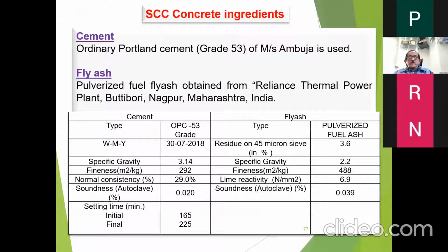Ordinary cement was used. The fly ash used was from Reliance Thermal Power Plant near Nagpur, Butibori, and the cement was OPC 53 grade. The fly ash had a fineness of 488 Blaine, or we can say meter square per kg, and the fineness of cement was 292. The fly ash requirement as per the code is that it should be more than 300. We have got a very good fine fly ash which was used.